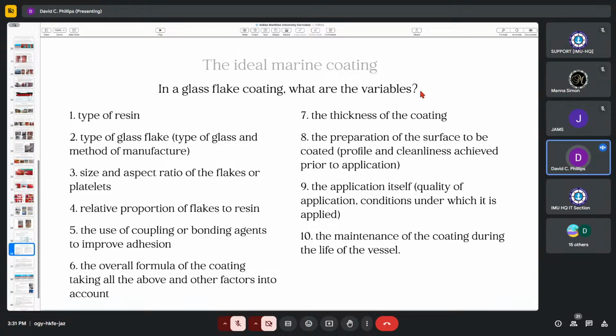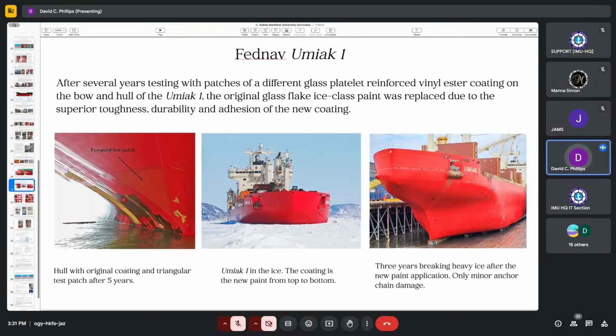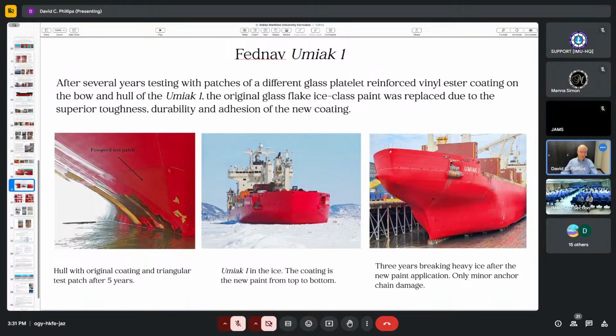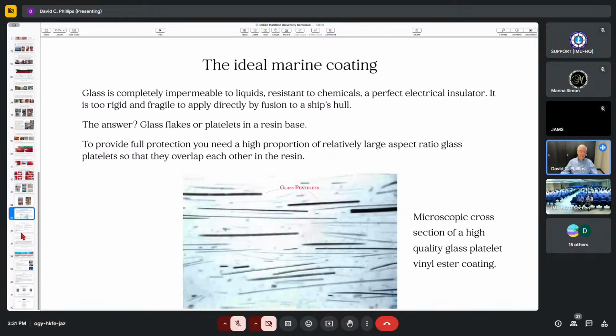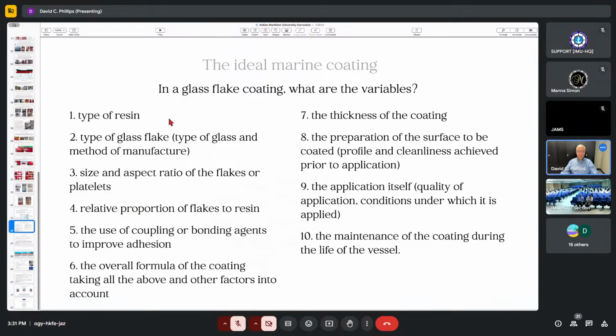Because I'm going to tell you straight, this ship originally had, that original coating is, quote unquote, glass flake vinyl ester. So how come that glass flake vinyl ester didn't hold up and this glass flake vinyl ester did hold up? Well, that has to do with the variables. The variables of a glass flake coating are the type of resin used, the type of glass flake, how it's manufactured and what kind of glass, the size and aspect ratio of the flakes or the platelets.